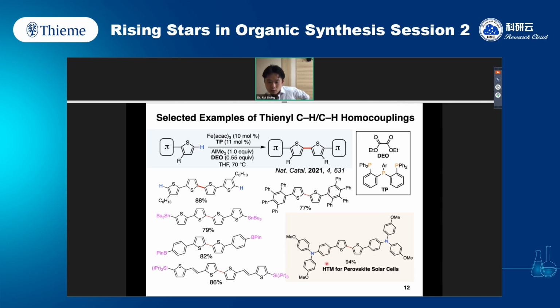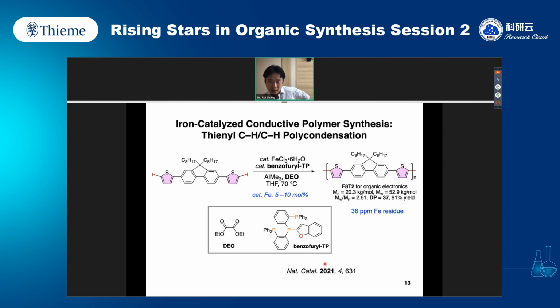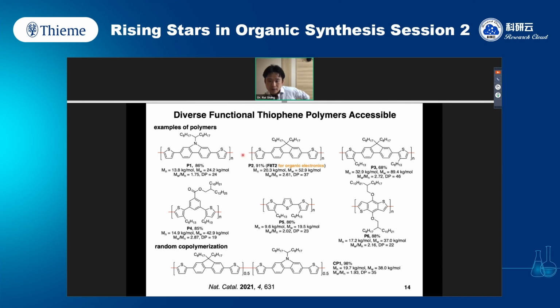By using this reaction, we can make this electron-donating hole transporting material for perovskite solar cells. Many of the tridentate phosphine ligands actually fail in polymerization. By using this benzofuryl-substituted tridentate phosphine ligand, finally the polycondensation works smoothly. We can reduce the iron residue to very low content, with less than 40 ppm of iron residue detected in the final polymer. The generality of the polymerization is a very important issue. We know that is a problem for radical and Stille-type polymerizations, which limits the monomer scope.